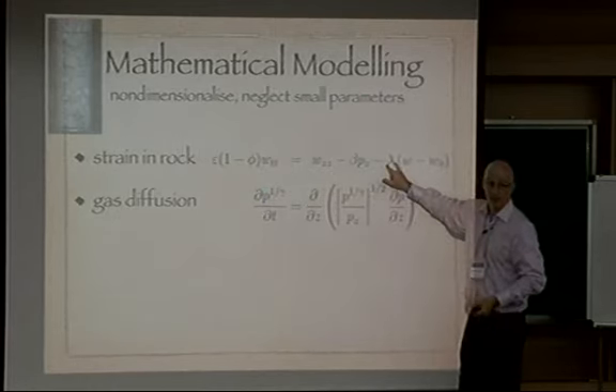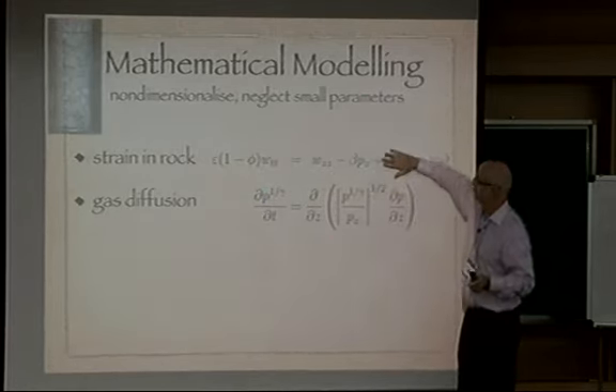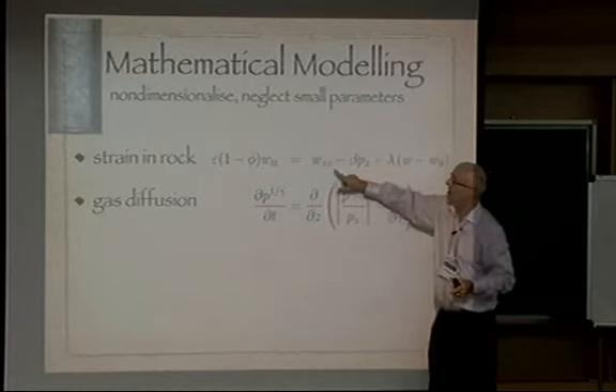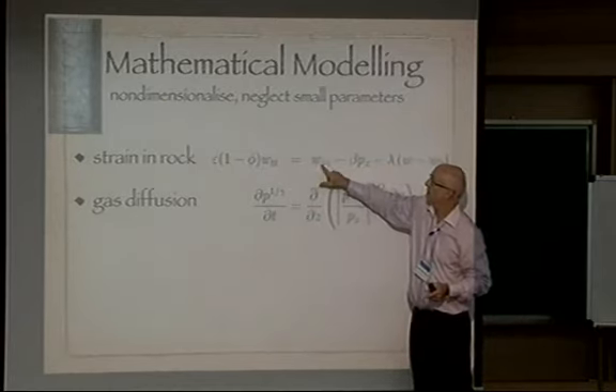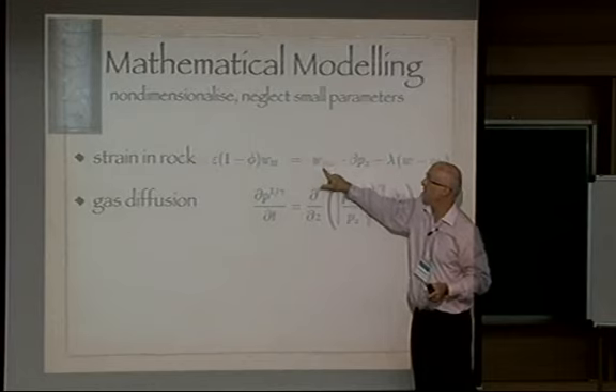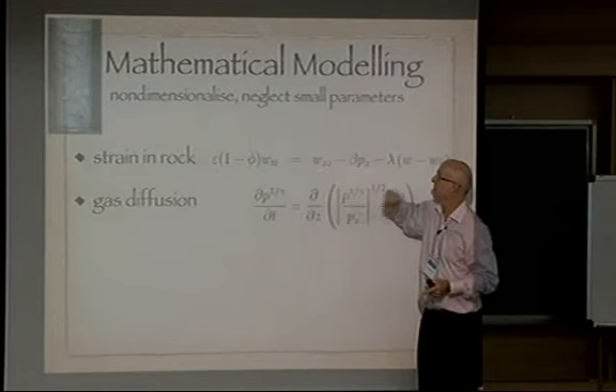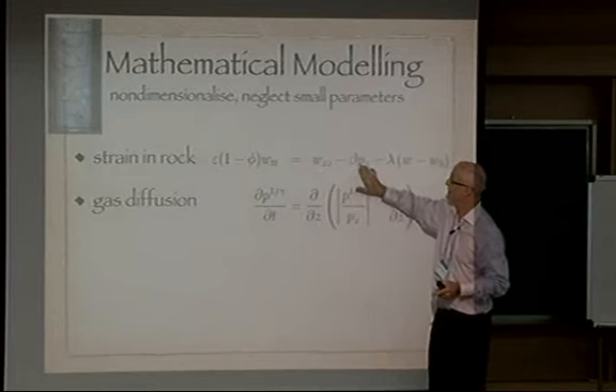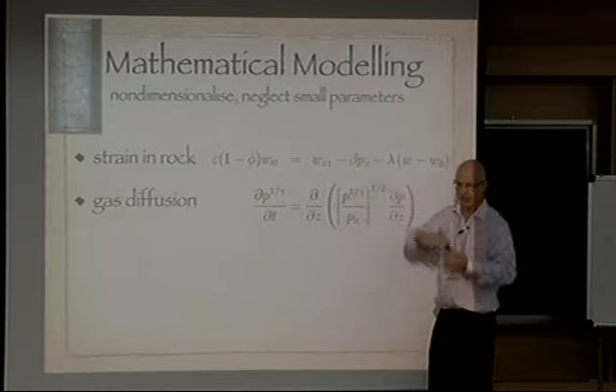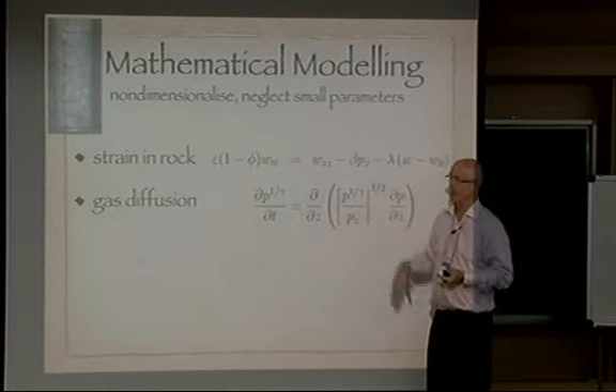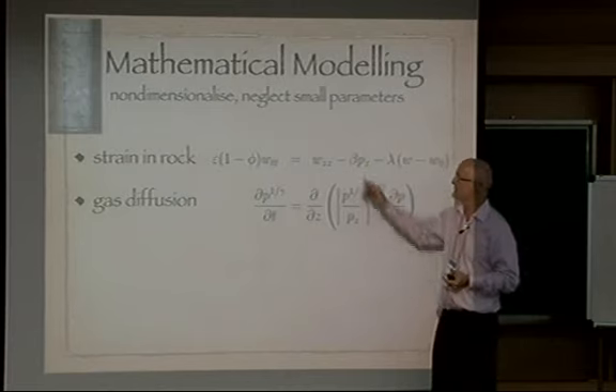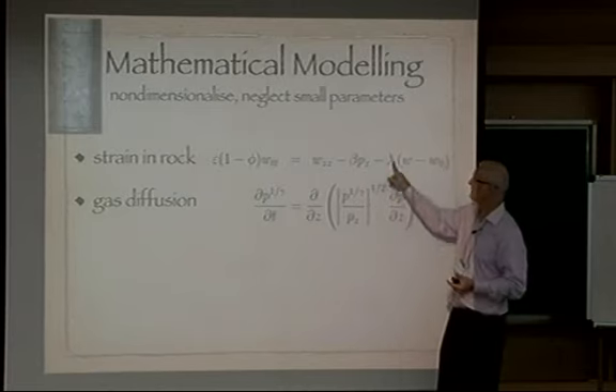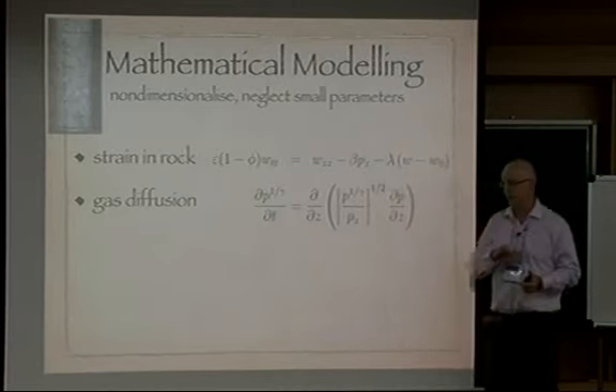The lambda, by the way, is the glue. With no lambda, you just get R. The rate of change of the divergence of W, the stress, is given by the pressure gradient. Of course, pressure gradient gives you stress. Then we ask where's the maximum pressure gradient. It turns out to be at the bottom, unless you have the lambda term in there. Then that modifies it.